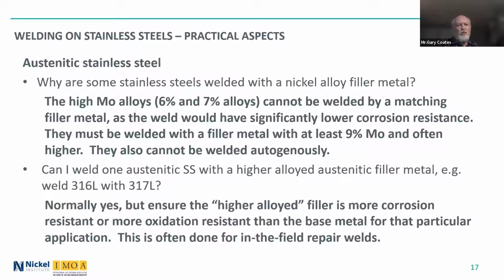You do have to ensure when we say higher alloyed filler that it is actually more corrosion resistant, or more oxidation resistant if it's a high temperature application, than the base metal for that particular application. In general, 317L is more corrosion resistant than 316L, so 99% of the cases that's valid, but you have to be aware of the exceptions.